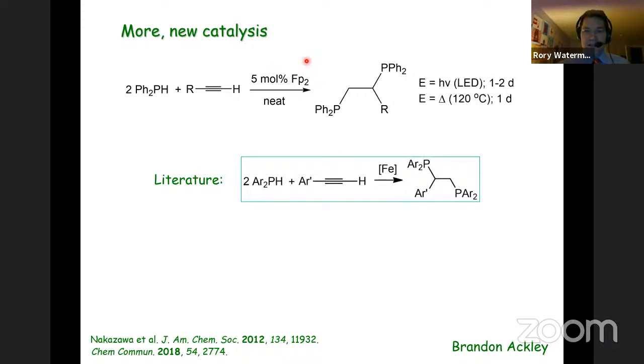And what we identified in this reaction is that under irradiation, we were now seeing the chemistry turn over in a couple of days, versus 3 or 4 days for Nakazawa's system. And then if we ran the reaction thermally, we were seeing conversion in about a day. And the thermal reaction actually is simply faster than the photochemistry to generate the 17 electron species. And so there's no reason to think that anything is different here, that we're not getting P-H activation via cooperative processes, 17 electron iron intermediates.